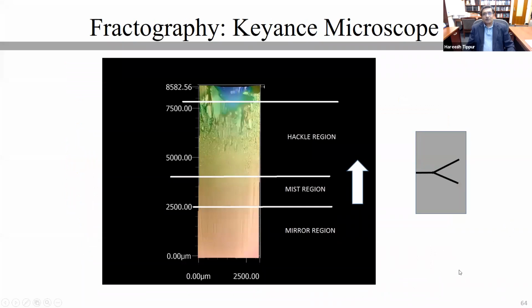So at this stage, I'm going to switch over to fractography. Before I talk about fractography, the emphasis is the precursors that we have identified in this talk at least, are three precursors. One of them is slowing down of the crack velocity before branching, the drop in the crack velocity from 1500 to 1000 meters per second. And the doubling of the effective stress intensity factor by a factor of 2, and the sigma hat value somewhere in the range of 17 to 19 megapascals.